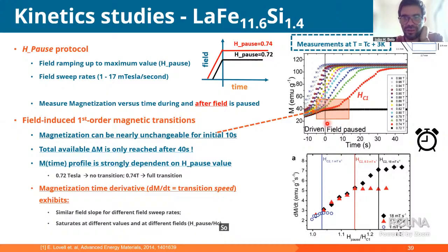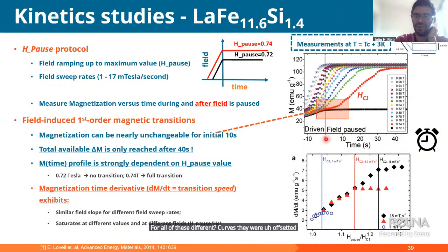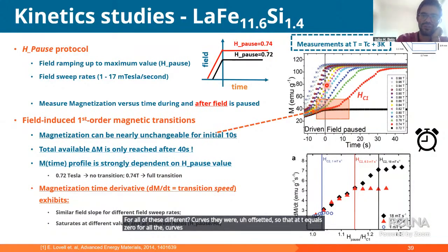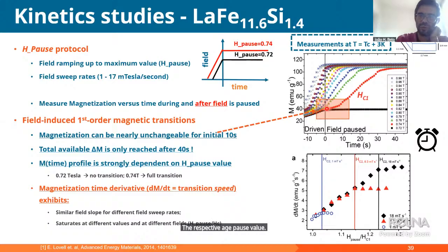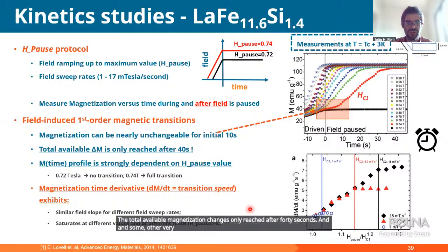So here are their results at that time, magnetization versus time for different H-pauses, where you can see that all of these different curves were offset so that at t equals 0, the field reached the respective H-pause value. So this means that all that you see after t equals 0 is magnetization evolving just as a function of time. There are very interesting features here. The magnetization can be nearly unchanged for the first 10 seconds. The total available magnetization change is only reached after 40 seconds, and some other very interesting points.